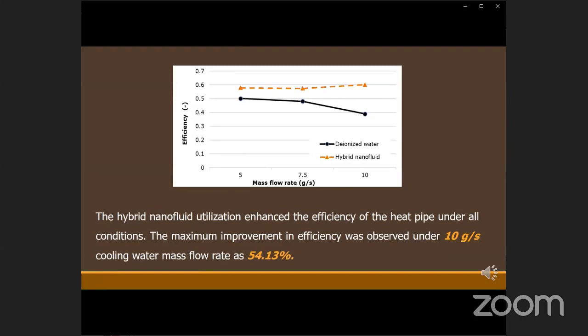The hybrid nanofluid utilization also enhanced the efficiency of the heat pipe under all conditions. The maximum improvement in efficiency was observed under 10 gram per second cooling water mass flow rate as approximately 55%.